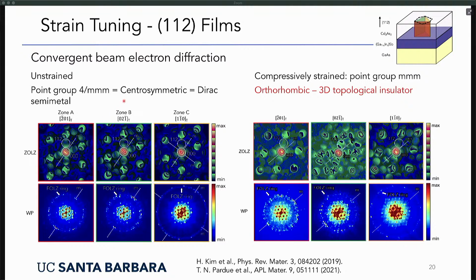And this on the left is a relaxed film, unstrained. And what we found from analyzing these patterns is that the point group is 4/mmm. That's a centrosymmetric point group, so we have the Dirac semimetal. Okay, then we can take this film and use our buffer layer to have a lattice parameter so that the cadmium arsenide is under compressive strain in this case. Given that the film is 112 oriented and the fourfold rotational symmetry axis is inclined in the film plane, as soon as we apply a biaxial in-plane stress, we would expect that this fourfold rotational symmetry does not exist anymore, right? This is something you would just expect based on basic considerations, and this is exactly what we find. So we lose the fourfold symmetry axis, and our point group is